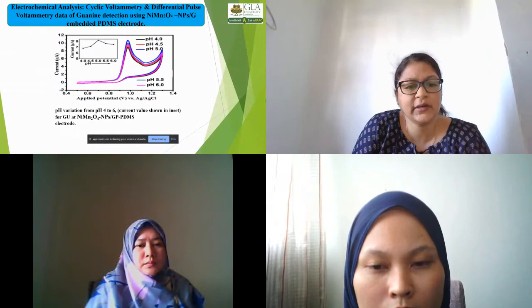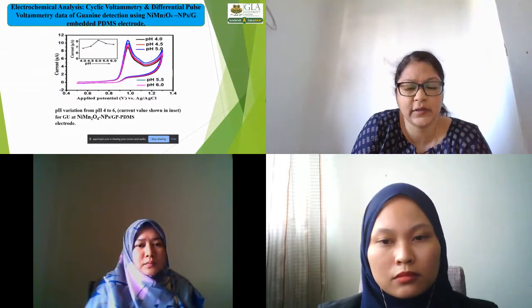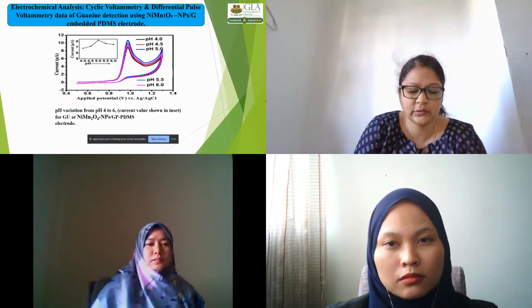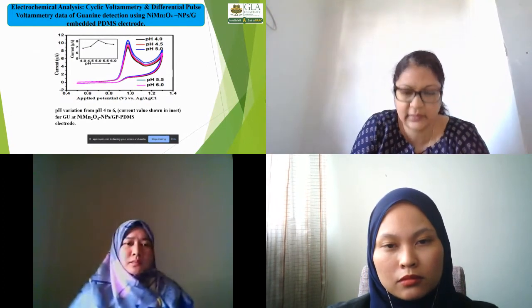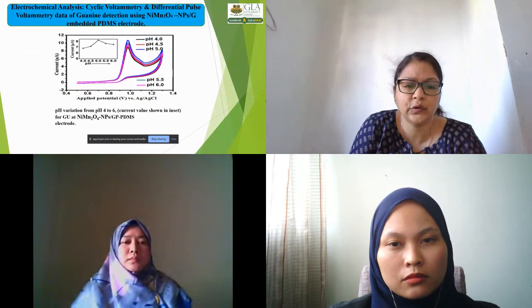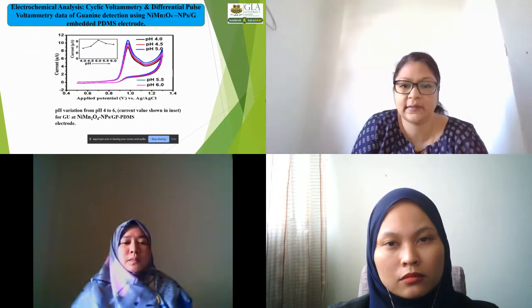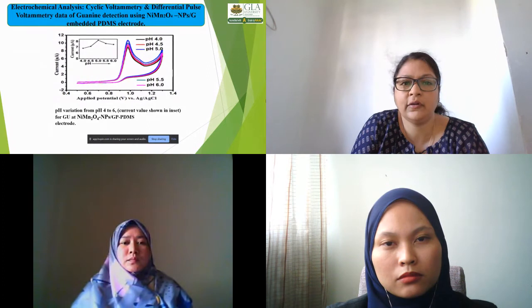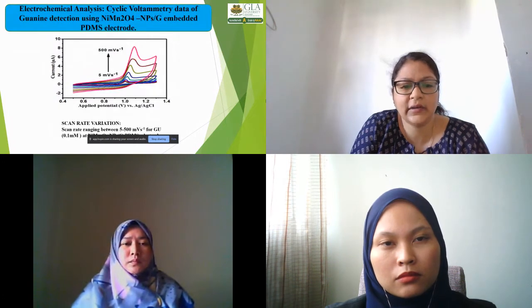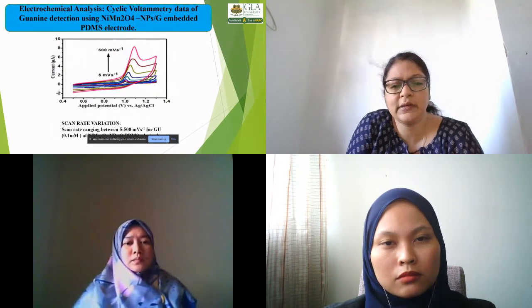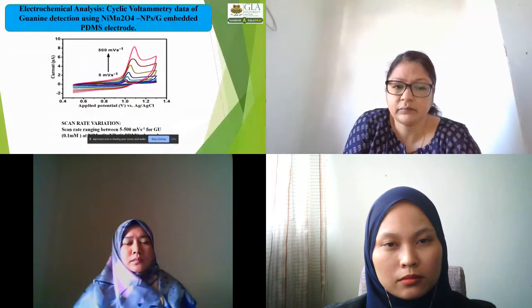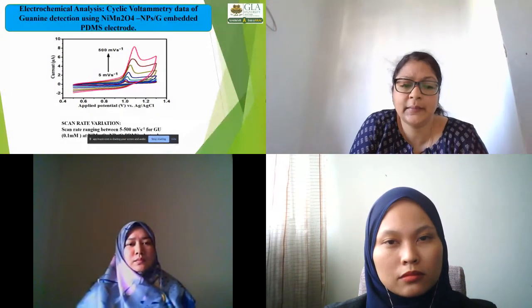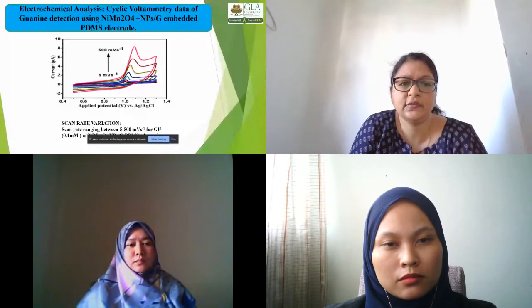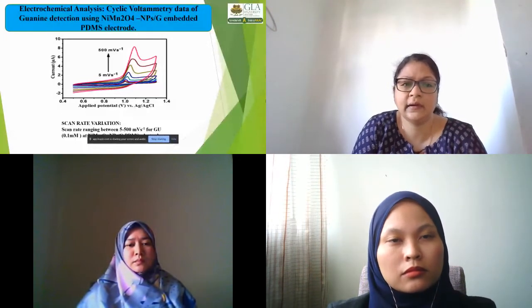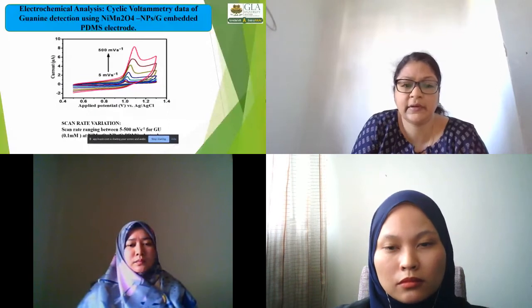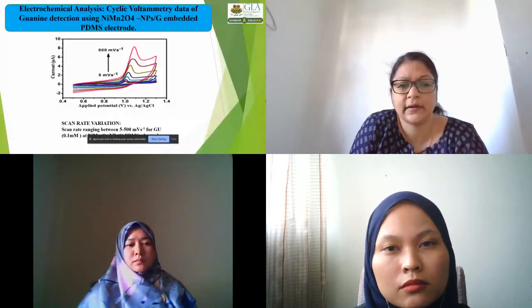Then we did pH variation studies from pH 4 to 6. Beyond 6, due to hydroxyl ion interference, it didn't give good peaks, but from 4 to 6 it gave very good results. And we also did a scan rate variation from 5 to 500 millivolts per second for guanine at 0.1 millimolar concentration, and it also gave a good rise in current as we varied the scan rate.